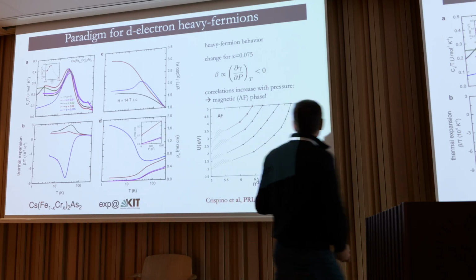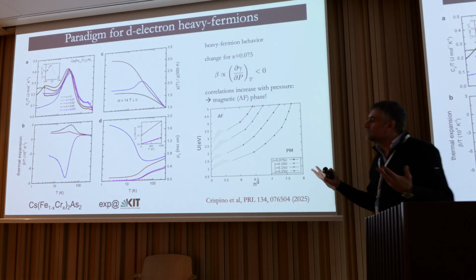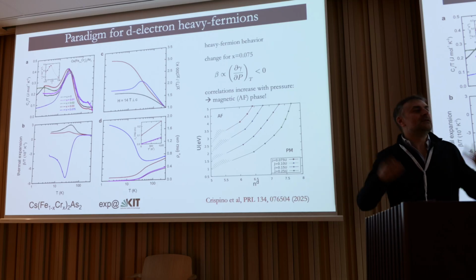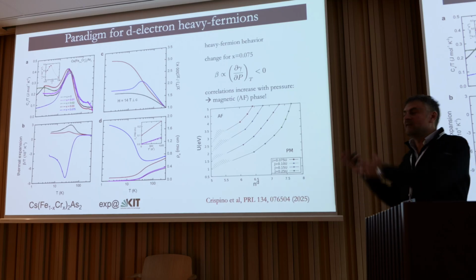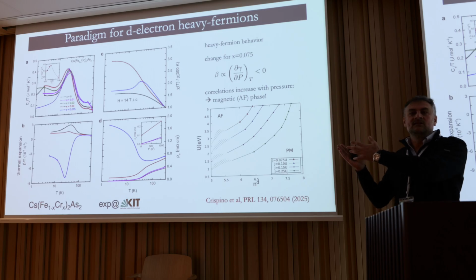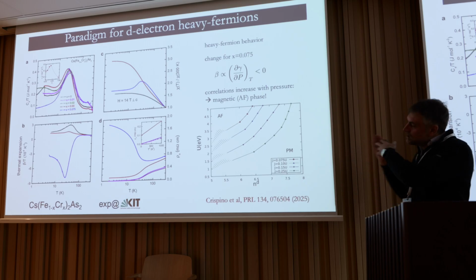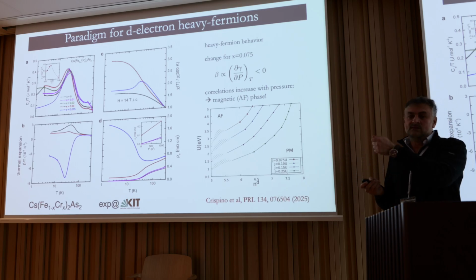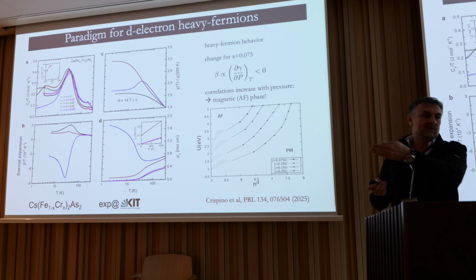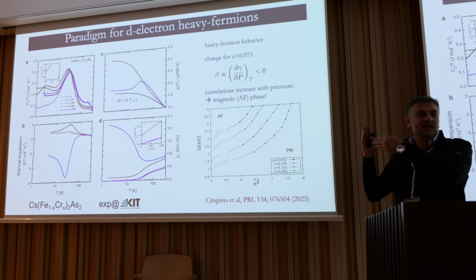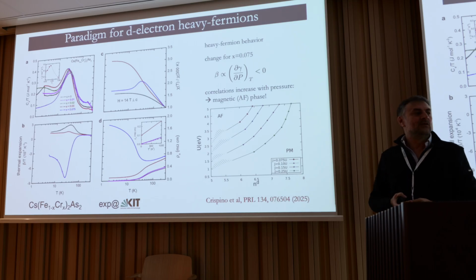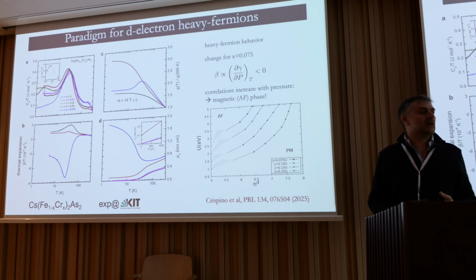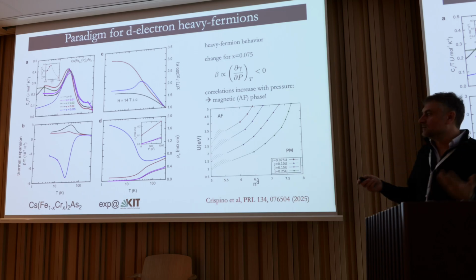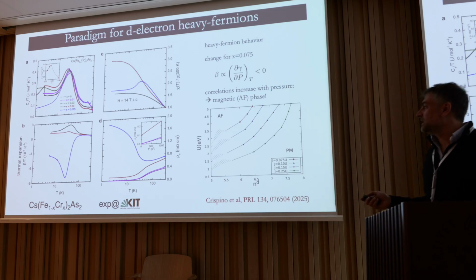So in the end, we obtain a phase diagram similar to the famous Doniach phase diagram. You have increasing masses and increasing correlations going with the knob that we tune, which is doping in this case. And at some point, this extreme enhancement of the masses is cut off by the appearance of a magnetic phase, the prevalence of the magnetic correlations.